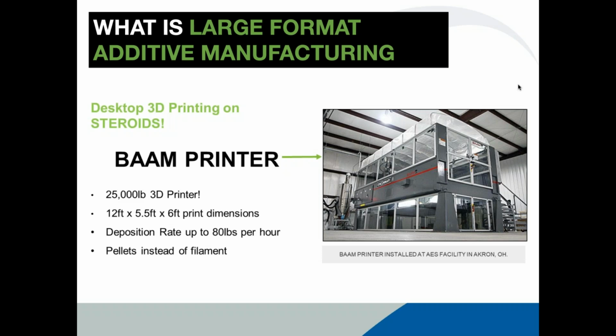We deposit material, all plastic materials, up to 80 pounds per hour. So we're pushing a lot of plastic out, and therefore that's how we can print very fast. So beforehand, you saw the material on the desktop 3D printer. It's called filament, and it kind of looks like a weed whacker spool. And instead of a filament, we actually use pellets. They're some of the same pellets that are used in the injection molding process. So we buy them in, you know, 1,000-pound boxes, and that's how we feed our printer material.